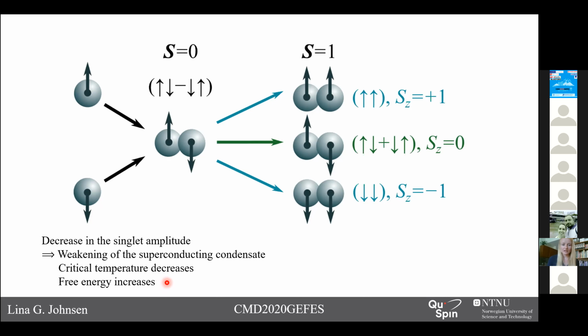So how do we manipulate the singlet amplitude? We do this by combining the superconductor with another material so that superconducting Cooper pairs can leak into the other material. And also, if this material introduces some kind of symmetry breaking, we can create equal spin and opposite spin triplet Cooper pairs from the singlets.